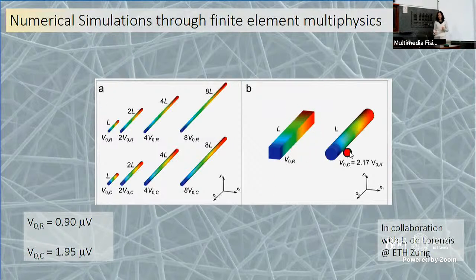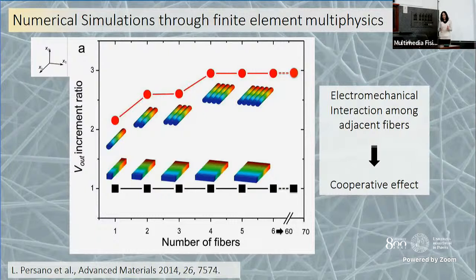And so we found that cylindrical fibers generate much higher voltage with respect to a rectangular cross-section. Finally, when building our array, we take a fiber, we put another one close, another one close. What happens is that we do not register any voltage increment in the case of rectangular cross-section fibers. On the contrary, if we have a cylindrical fiber, there is an increment of the voltage output.